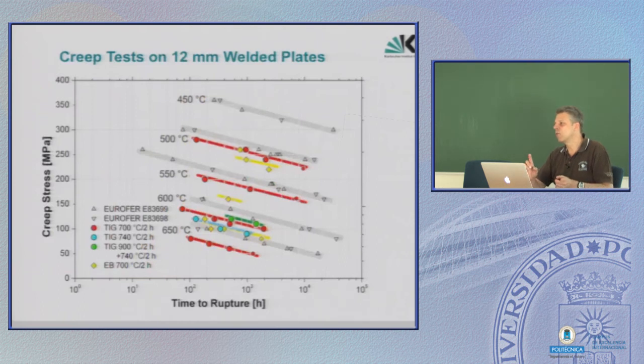A much more complicated problem is then connected to creep, because all these boxes are stressed under high temperature, so creep has always to be taken into account. And also here, just the broad picture. We made many creep tests at various temperatures. Operating temperature finally would be not higher than 550 C, but to speed up creep tests, you don't always have years of time to wait until the end of the creep test. That's why you perform them also at higher temperatures.